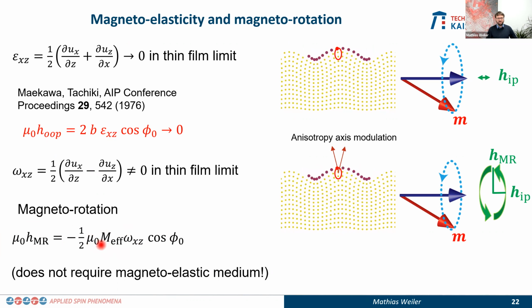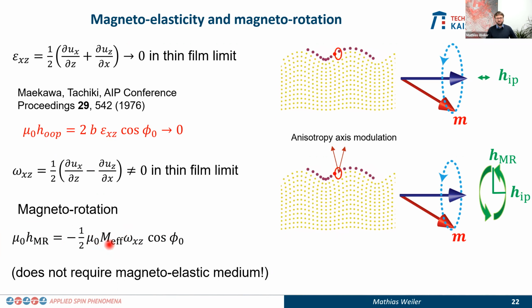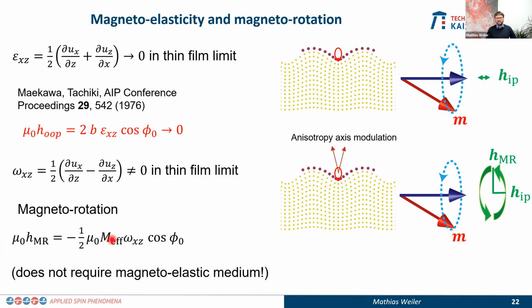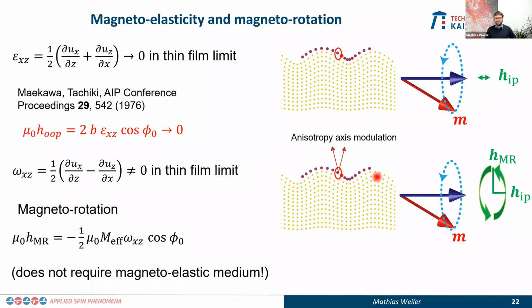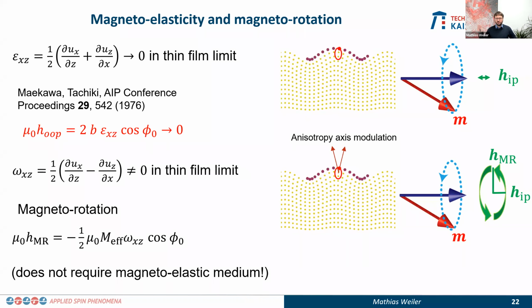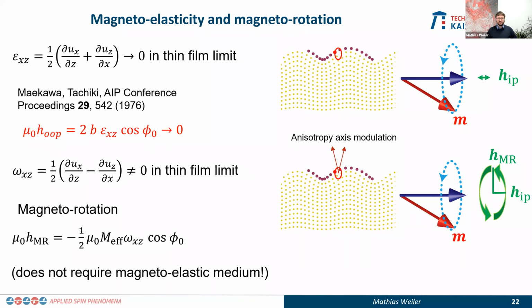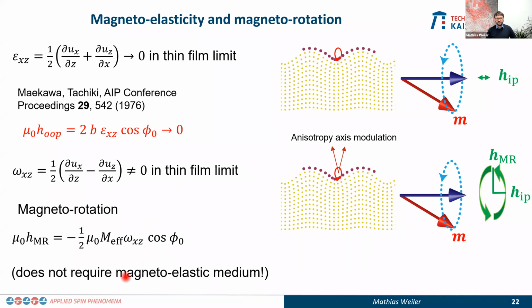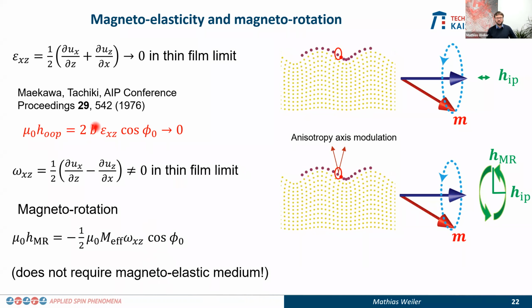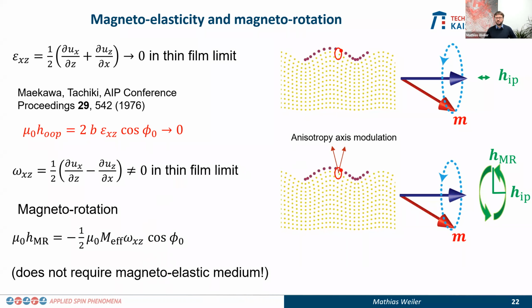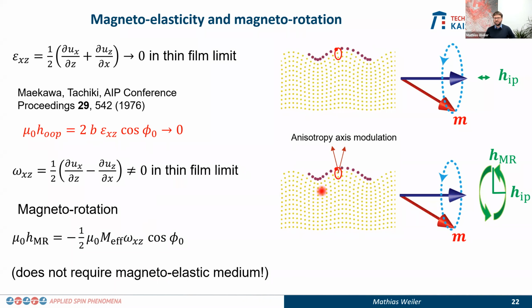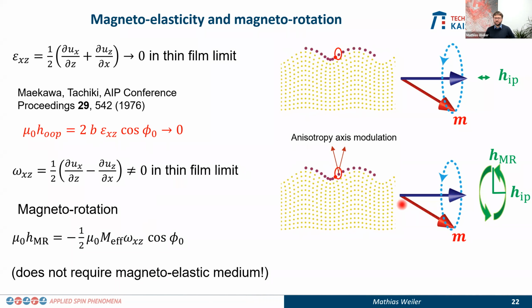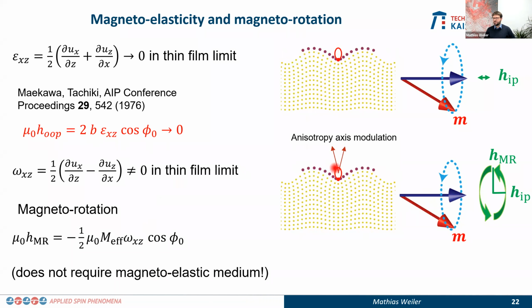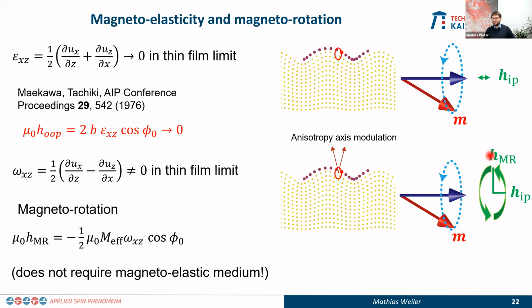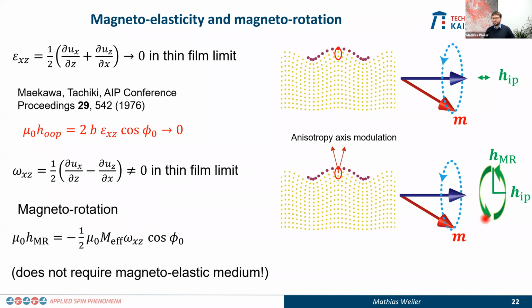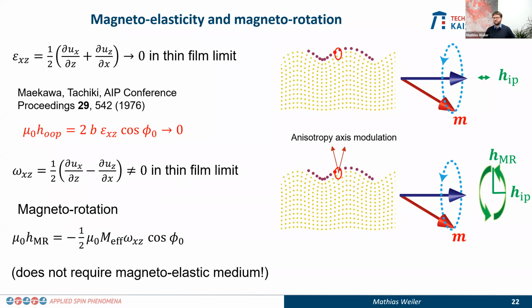Okay, and what's really funny about this magneto-rotation thing is it does not require magneto-elastic interaction, right? It's really just a modulation of the anisotropy axis. So this works even if your magneto-elastic coupling, which is described by the parameter B, is exactly 0. Okay, it does not require magneto-elasticity, does not require spin-orbit coupling. Okay? And that comes here to the rescue because this, well, recovers the elliptical precession of the total driving field. Okay?